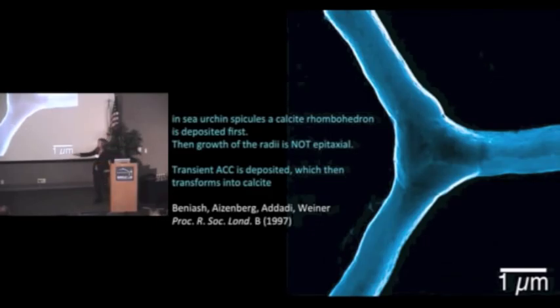It's actually amorphous material that's deposited first, one about 100 nanometer size nanoparticle at a time. Space is entirely filled, and finally, crystallinity propagates through the fully formed aggregate. So this amorphous phase that's deposited is transient. It's just this trick that the cells had developed to deposit more material faster. Spicules were the first biominerals in which these very good friends and colleagues of mine discovered for the first time that there are indeed amorphous precursors to biomineral formation.